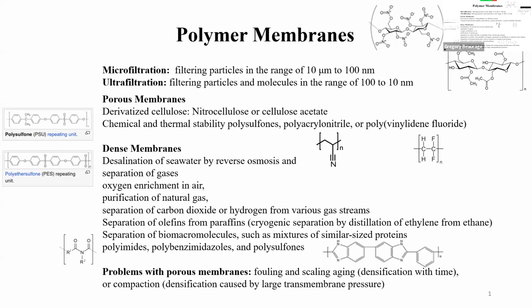You can do it by taking a plastic film and blasting it with ions to get smaller pores. You can do it by taking a polymer in a solvent and then dumping it into a non-solvent. So that's a really popular method. And that's what these guys in California ended up doing to make this reverse osmosis membrane: non-solvent induced phase separation membranes. So that's an industrial process. And later, this is at the end of World War II, like 1949, 50, and then into the 60s, this Millipore company was getting money and grew into the biggest company in the business for doing that.